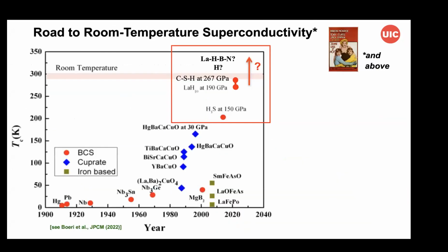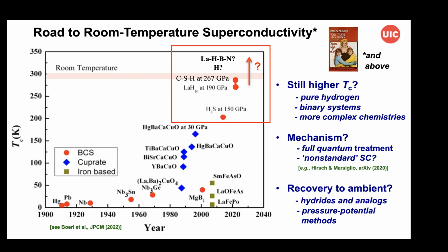So just to conclude, here's what I've just talked about in terms of the lanthanum, the CSH and the H3S systems as a function of pressure, a Tc plot versus year, comparing the Tcs we now have in these systems with the historical record going back to the original discovery of superconductivity, focused on the high Tcs in pure hydrogen, binary systems and more complex chemistries. The mechanism, and I've been arguing that one needs a full quantum treatment, and this may be relevant to some of the questions in the literature about the nature of these conventional superconductors, and perhaps we need a new language to describe them. And I rather like the approach of calling these non-standard superconductors, superconductors nonetheless, but perhaps of a different flavor, because we're in a completely different regime of temperature, and we have a highly quantum and anharmonic system. And I made some comments about recovery to ambient.